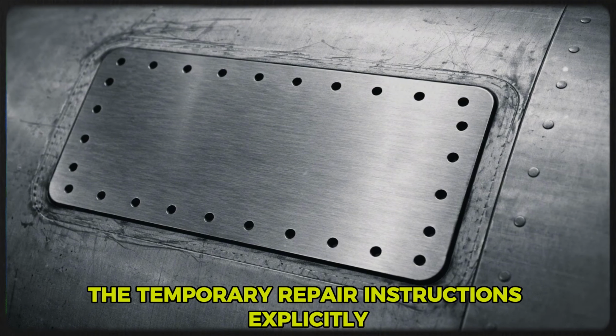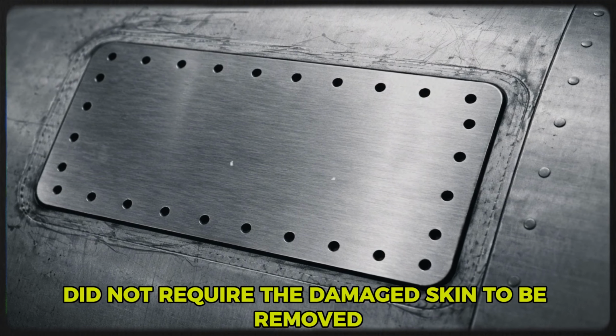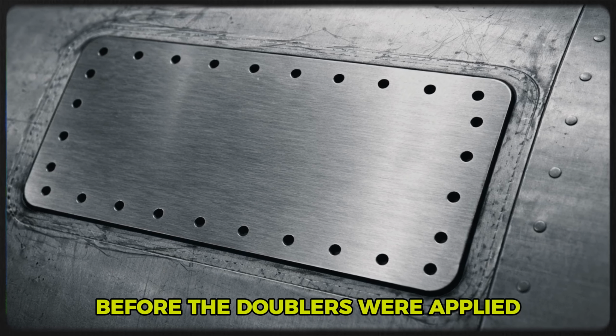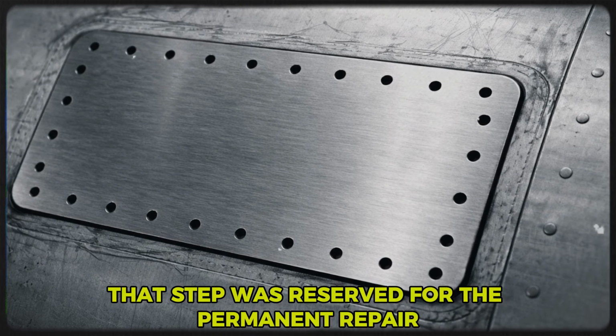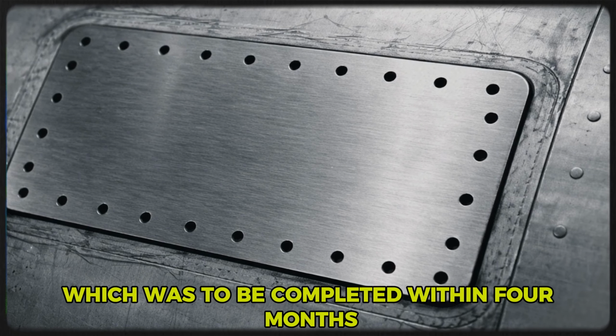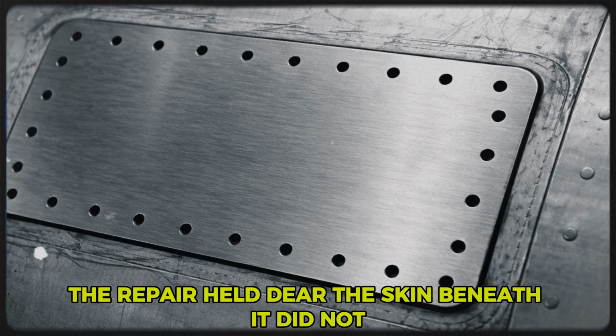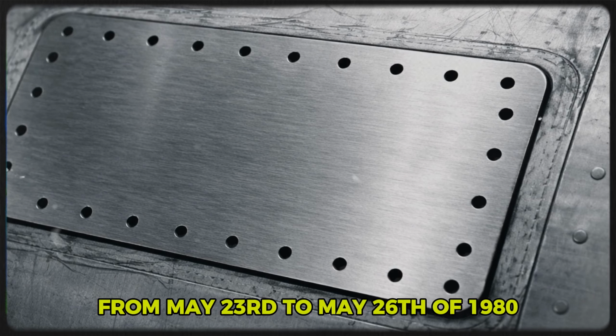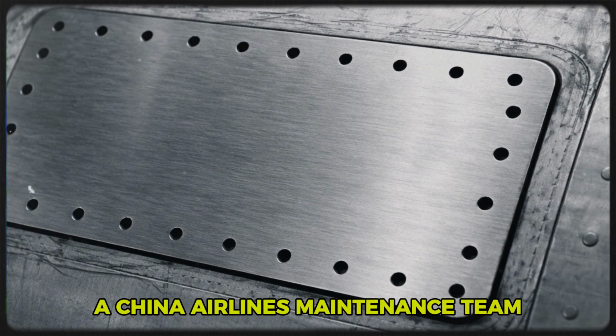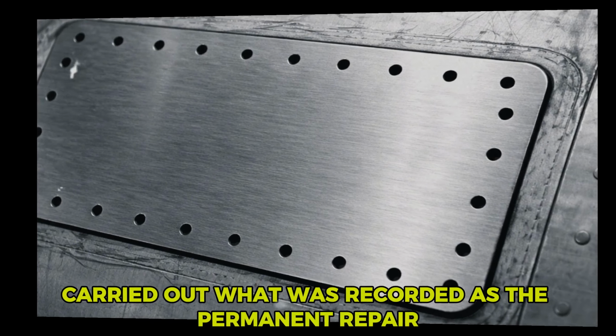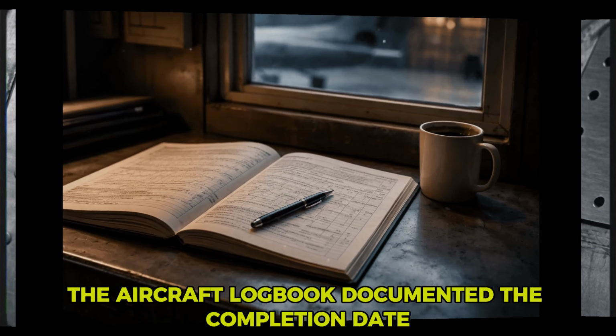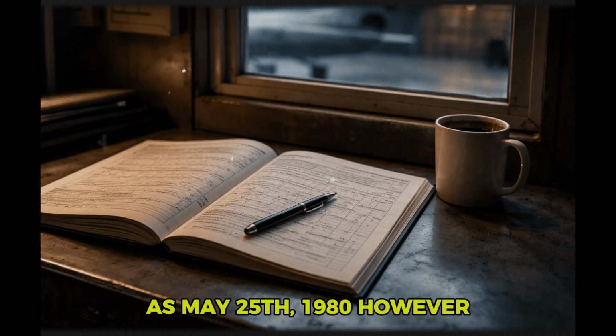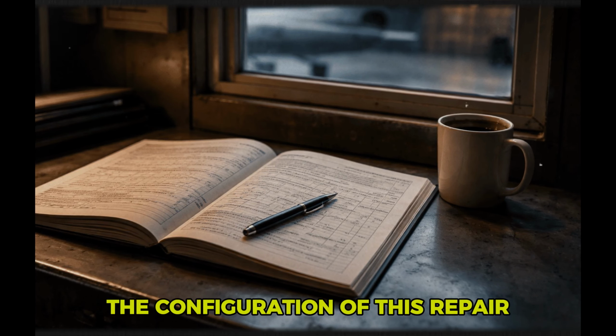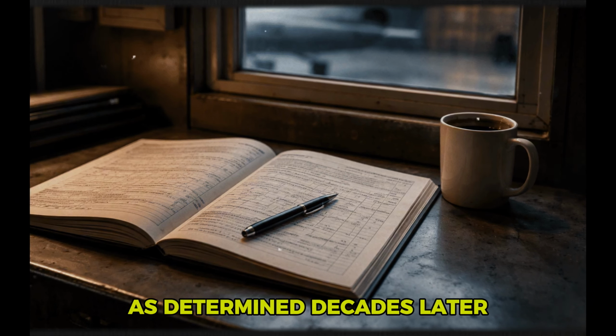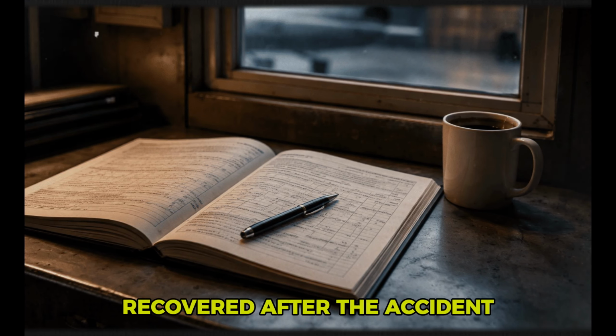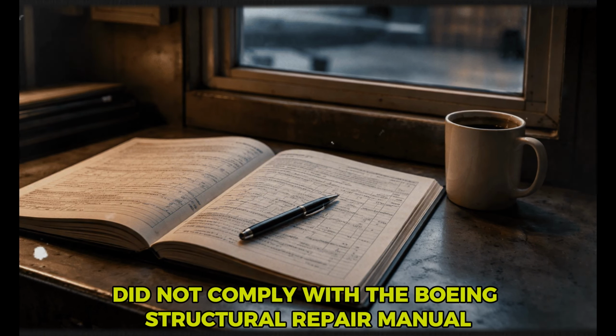The temporary repair instructions explicitly did not require the damaged skin to be removed before the doublers were applied. That step was reserved for the permanent repair, which was to be completed within 4 months. The repair held. The skin beneath it did not. From May 23rd to May 26th of 1980, a China Airlines maintenance team carried out what was recorded as the permanent repair. The aircraft logbook documented the completion date as May 25th, 1980. However, the configuration of this repair, as determined decades later from the physical evidence recovered after the accident, did not comply with the Boeing Structural Repair Manual.